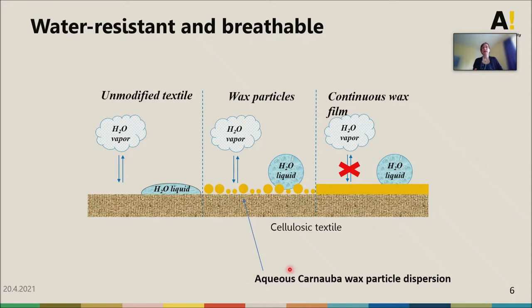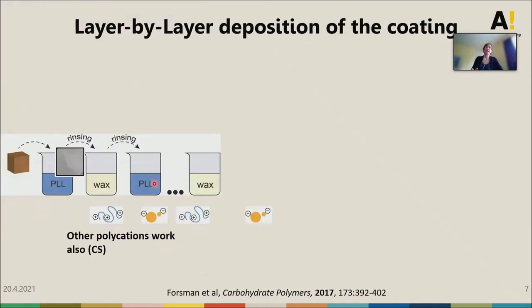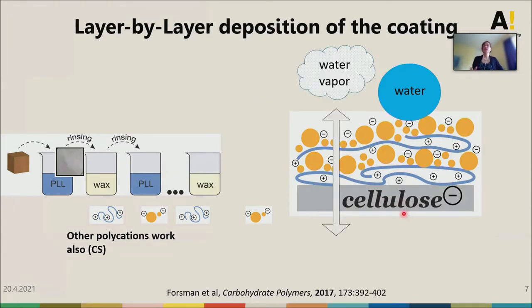And this we did using an aqueous carnauba wax particle dispersion. The way it's done is by layer-by-layer deposition, but this can also be done by spraying or brushing. So it's very simple. You can take the wood or the textile and dip it into an aqueous cationic polyelectrolyte solution, or a protein. In this case, we used polylysine. And then that changes the charge of the cellulose to positive, and then the anionic wax particles adsorb onto the layer, and you can add as many layers as you want. You don't need many layers for it to be efficient. So this is quite a simple and straightforward way, and we're only using natural materials to get the hydrophobicity.